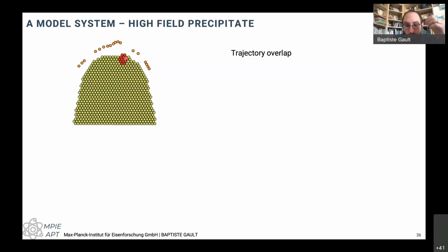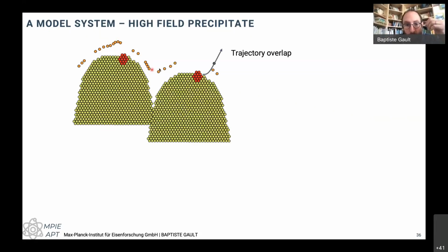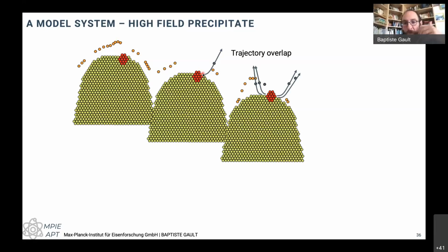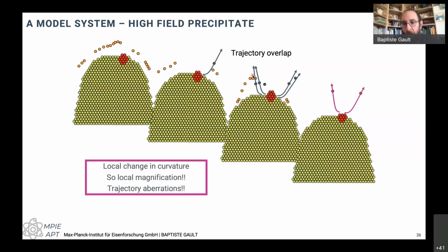And we need to have basically locally a higher curvature forming to increase the field. And once the field is high enough here, I might be in a position where I can start to remove the atoms from the precipitate. But in between, this higher field is going to push some of the atoms from the matrix very close to the particle. They're going to be pushed away a bit further than they should. And then the atoms from the particle itself also are going to be pushed away slightly more. So there's another limit of resolution, which is not just from a pure metal matrix, but also as soon as we have microstructural features that are really what we're interested in.